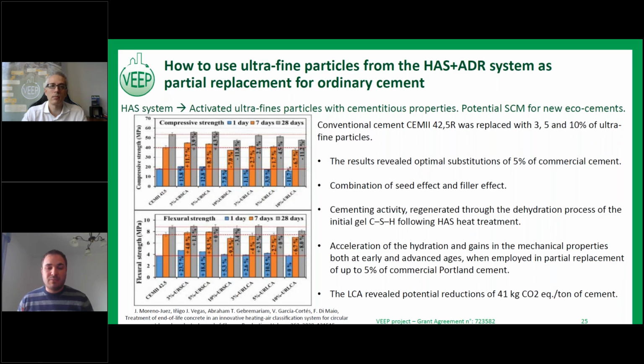And the third effect is that we regenerate the cementing activity of the ultrafine particles through the dehydration process applied by the heat treatment of the HAS technology. So the combination of the three effects induces an acceleration of the hydration process and a gain of the mechanical properties both at early age and advanced age. Finally, we have performed an LCA, life cycle assessment, of this new technology applied to the ultrafine particles in the new eco-cement, and we are able to demonstrate that the substitution of the cement was equal to the reduction of the CO2 emitted. In this case, we are able to reduce more or less 40 kilograms of CO2 per ton of cement.